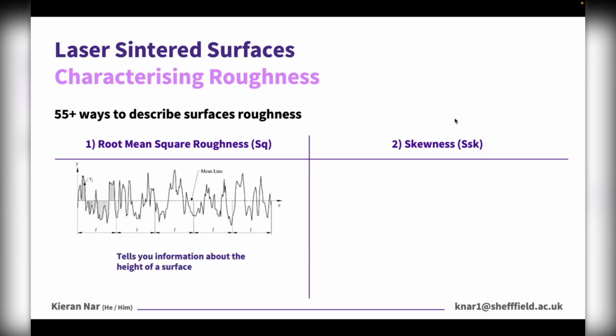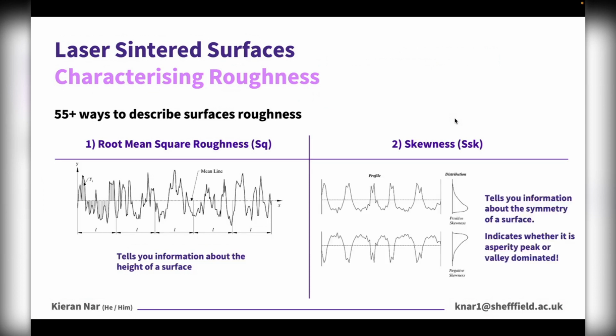So I imagine quite a lot of you are familiar with the term RMS roughness, but for those who might not be as well acquainted, RMS roughness tells you information about the height of a surface being evaluated. Skewness, on the other hand, is an amplitude density function, which tells you information about the symmetry of the surface being evaluated, and more generally indicates whether the surface being evaluated is asperity peak or valley dominated, as illustrated, or neither.